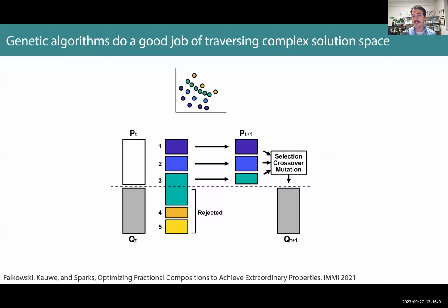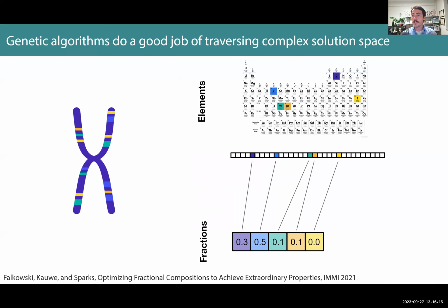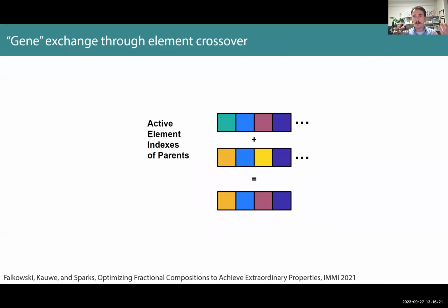The problem is that this process is kind of slow because there's selection calculations, there's crossover calculations, there's mutation calculations, each one of these. And you typically do this for a large population of materials, you know, 100 candidates. So these can be slow. That said, we gave it a shot. We represented our material with our composition-based feature vector. We came up with a mechanism whereby we could have crossover.